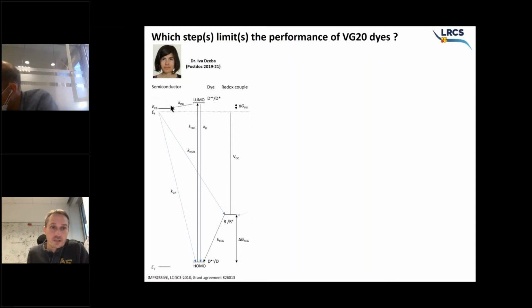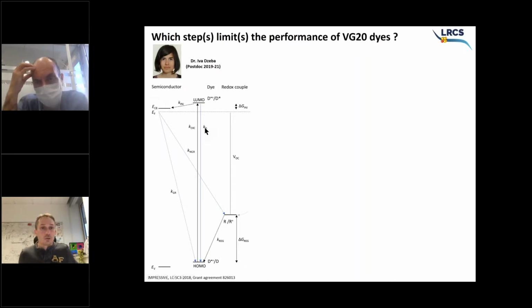You excite, it injects, so you have an injection rate, but this injection is in competition with the excited state lifetime, which can be problematic, knowing that the excited state lifetime is only 400 picoseconds in solution. But I should also say that when it's in the self-assembled monolayer, it's more like 50 picoseconds than 400 picoseconds. Then you have introduced this electron in titania.